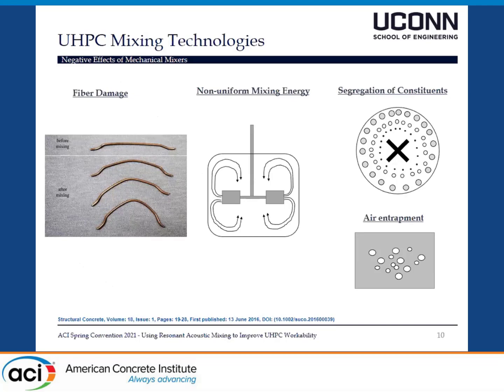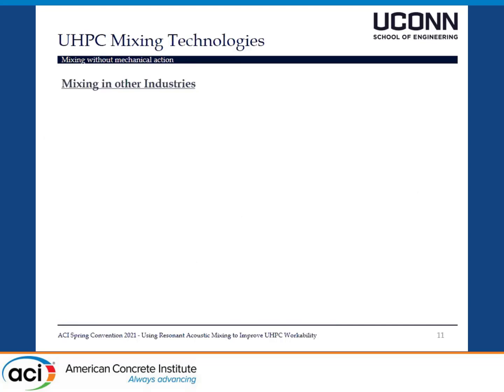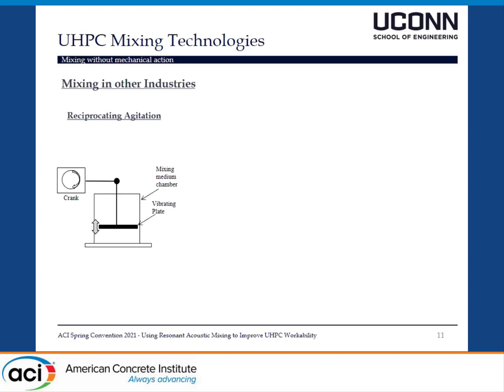And so the good question to ask then is, can we mix UHPC without a mechanical tool so that we can avoid these issues or at least mitigate them? A good point to answer this question is to look at the type of mixers that are being used in other industries. For example, in the powder and pharmaceutical industries, they use reciprocal agitation mixers. The constituents lie in a chamber right here, and there's a vibrating plate that is moved up and down. And what happens is a pressure wave is pushed through the medium to induce mixing.